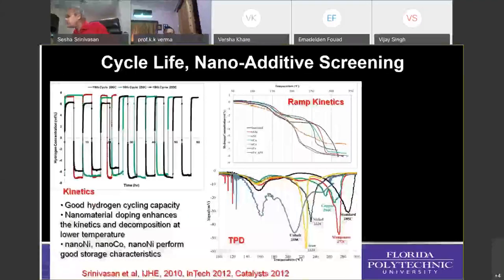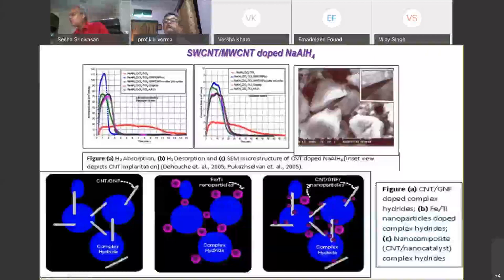And then we tried to look for the cyclic stability of these materials. We also tried to add some nano catalysts like nano iron nickel catalyst or iron cobalt copper. We tried to look for the kinetics of the reaction and cycle life. And then my professor Onkar Srivastava published a paper in 2005 looking at the carbon nanotubes' impact on the complex borohydrides and complex aluminum hydride. We proposed the mechanism to have a nanotubular as well as nanoparticle structure so that you can have a better transport of hydrogen. At the same time, you can have a better reversible hydrogen behavior.